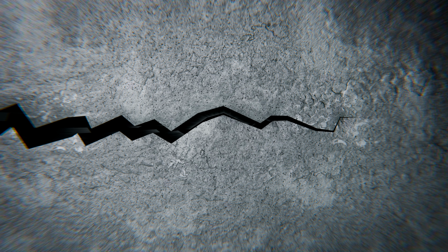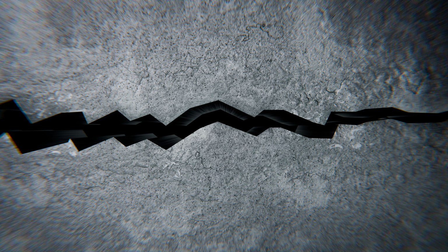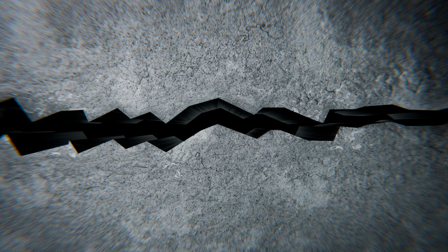And this is what makes cracks so dangerous. They create a large stress concentration that can cause a material to fail at an applied stress well below its yield or tensile strength, the properties we normally use to design structures. In theory, the local stress becomes infinite as the radius at the crack tip approaches 0. But in practice, when the peak stress reaches the material's yield strength, the material immediately ahead of the crack tip begins to deform permanently, redistributing the load and creating a region of plasticity called the plastic zone.